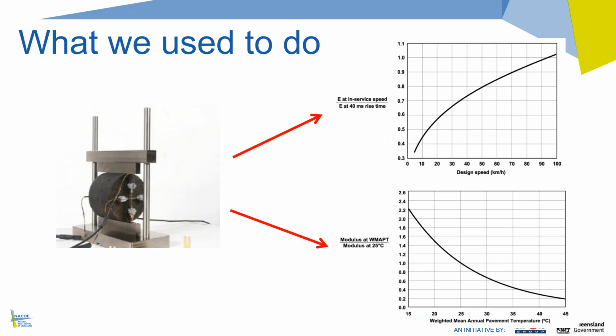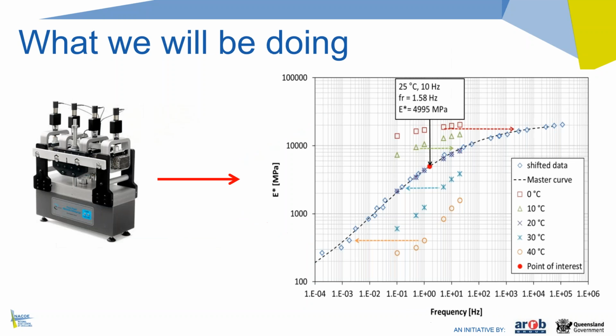Okay, so with that I'll start my presentation. So let's first recap what we used to do. So within the current Austroads design framework and the TMR supplement, resilient modulus testing. So we do a resilient modulus test at one temperature and one load frequency, and then we use the Austroads equations to predict from that one test result the flexural modulus of the material at a range of different temperatures and loading speeds. So that's what we're currently doing. So the important thing there is that we're testing in a single condition.